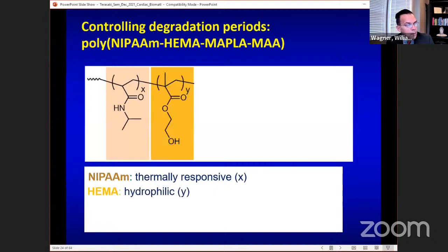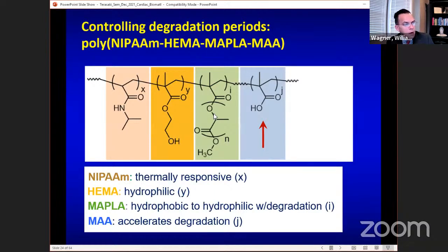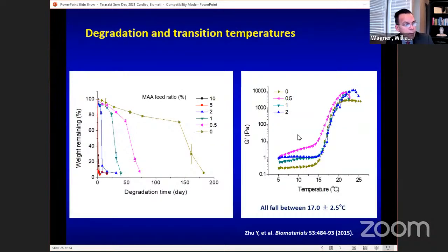Here's another example of some of the chemistry. So here we have 4 MERs that we're putting together, and we're changing the ratio of the methacrylic acid and the HEMA. So by changing that ratio and increasing the methacrylic acid, that is going to catalyze the cleavage of this polylactide right here. And that's the equivalent in this polymer, that pink strand. So the more of this, the more it should auto-catalyze and the quicker it should degrade. So what this is showing is that we can design polymers that all have a pretty similar phase change behavior.